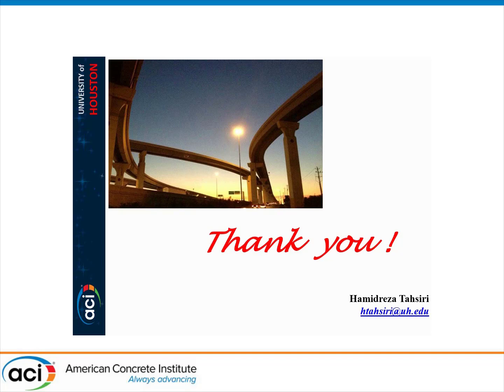Yeah, actually, regarding the relaxation, we don't have any specific equation in 440R. There have been several studies, but they don't have any equation to obtain the instantaneous relaxation of the system. So this is one of the missing portions. And regarding the harping, as I mentioned, this is based on previous studies conducted in 2000, and there is some other analytical work that was conducted after that, but this equation did not change after that time.